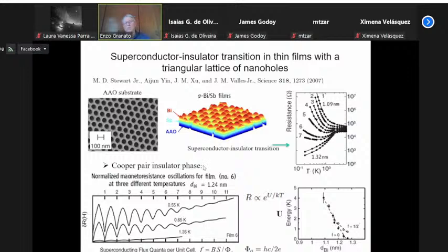And that's one of the reasons why this particular system, this particular geometry of a triangular lattice of nanoholes, has been used for the superconducting-insulating transition, because you can actually identify the superconducting phase and the insulating phase, whether it is made of Cooper pairs, bosons, or if it is made of a usual electron insulator.